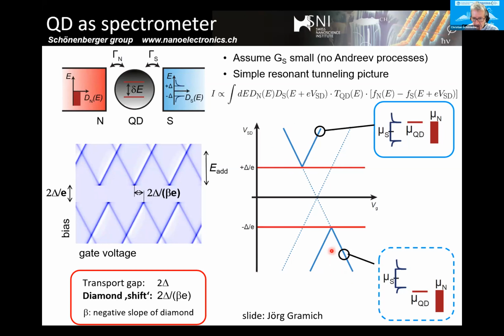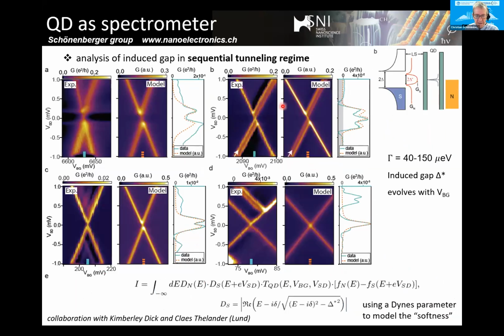Now, if there's a soft gap, if there's a normal state density of states in the gap, then the usual Coulomb blockade diamonds will be this, right? This dashed part. Then you see both the dashed part and the bold part. And that's exactly what you see here, right? This is exactly what I explained. And so you see there's a gap here of the right order, but there seems to be a similar density of states in the gap as outside. So that's why this line in the middle has the same intensity in this plot.